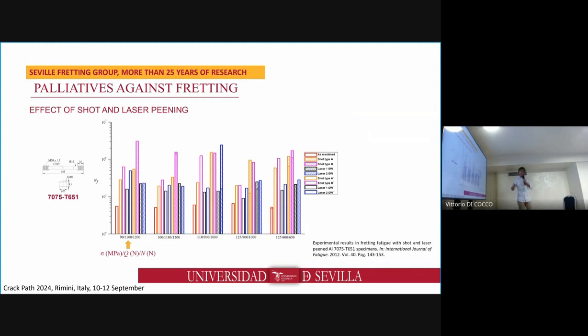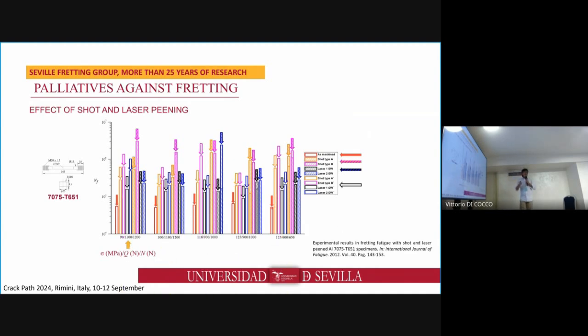To analyze this behavior more deeply, we did some fretting tests. Here in this plot, it's shown the fretting fatigue lives as a function of the fretting load and for different surface conditions. First, we have the baseline: those tests done with as-machined fretting fatigue test specimens. Then we have those tests done with laser and shot peened test specimens. And finally, we did some special tests in which the surface was minimally machined, just to remove the characteristic surface produced by shot and laser peening. We can see the important effect produced by the surface condition on the fretting fatigue, especially in the shot peened test specimens.